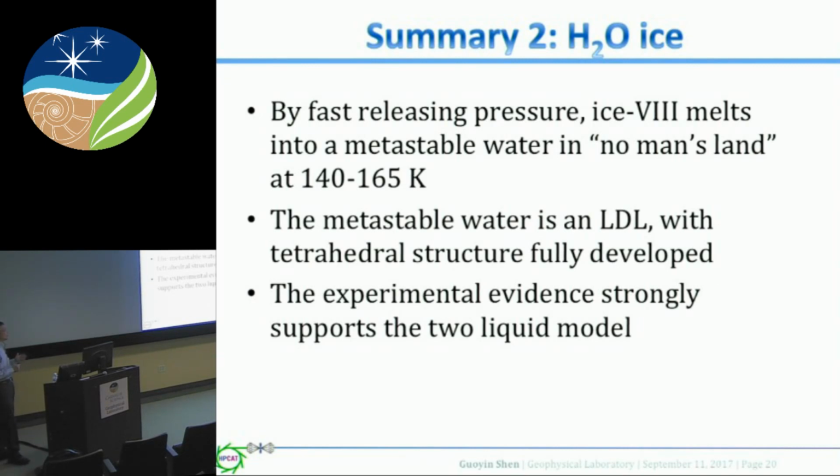And this experimental evidence strongly supports the two liquid model, because in the two liquid model we have to have a low density liquid, while the normal liquid is more on the high density liquid side. So far there's been a lack of experimental evidence for low density liquids. And with this metastable decompression approach, we actually observe that there is a metastable low density liquid there. So that's the contribution from this part.